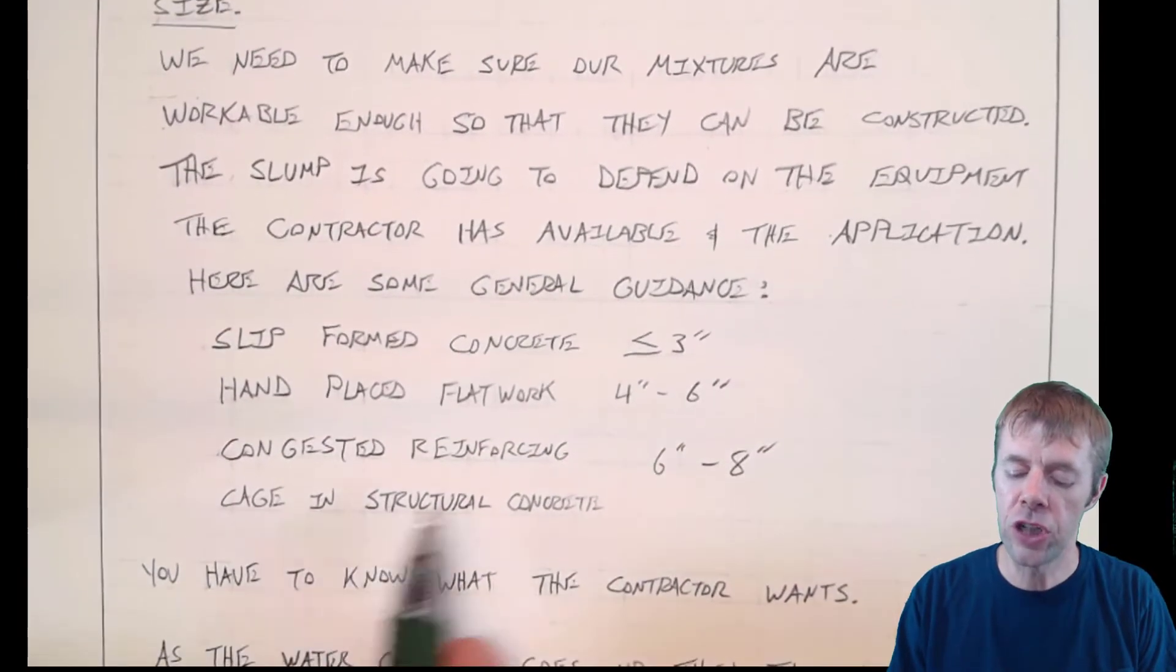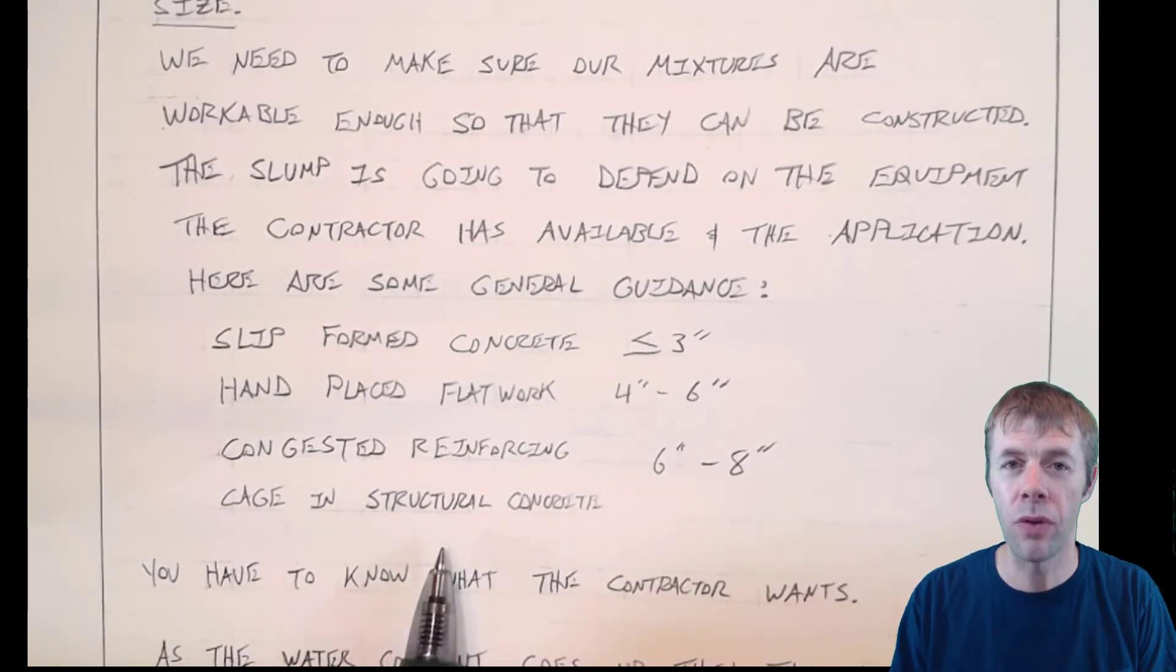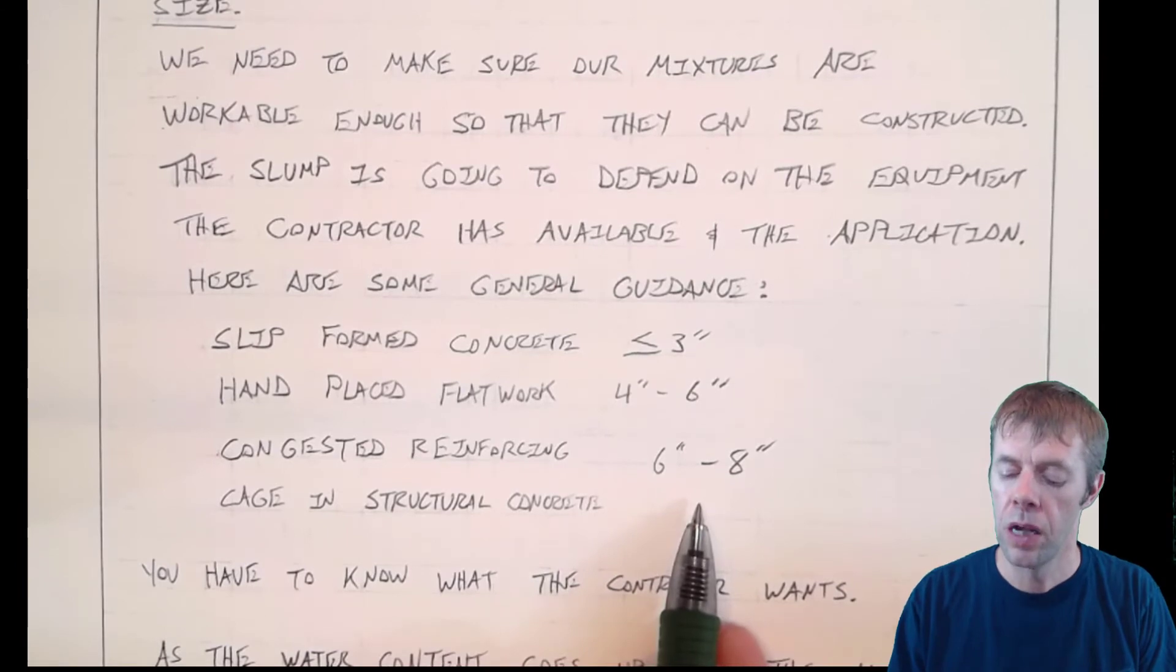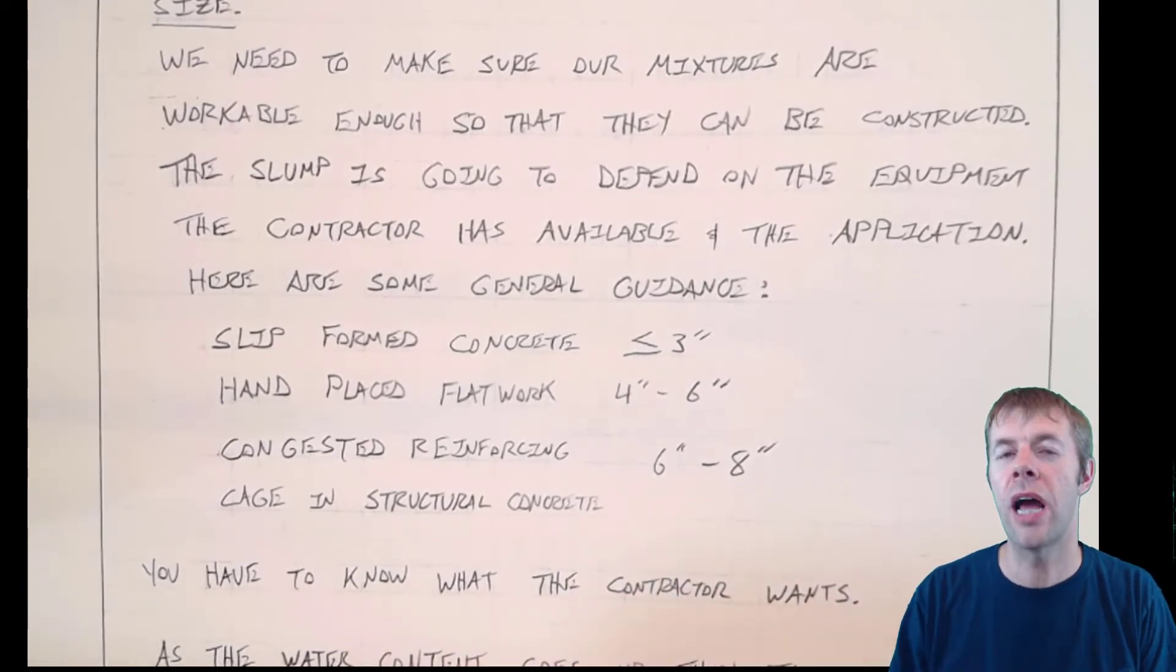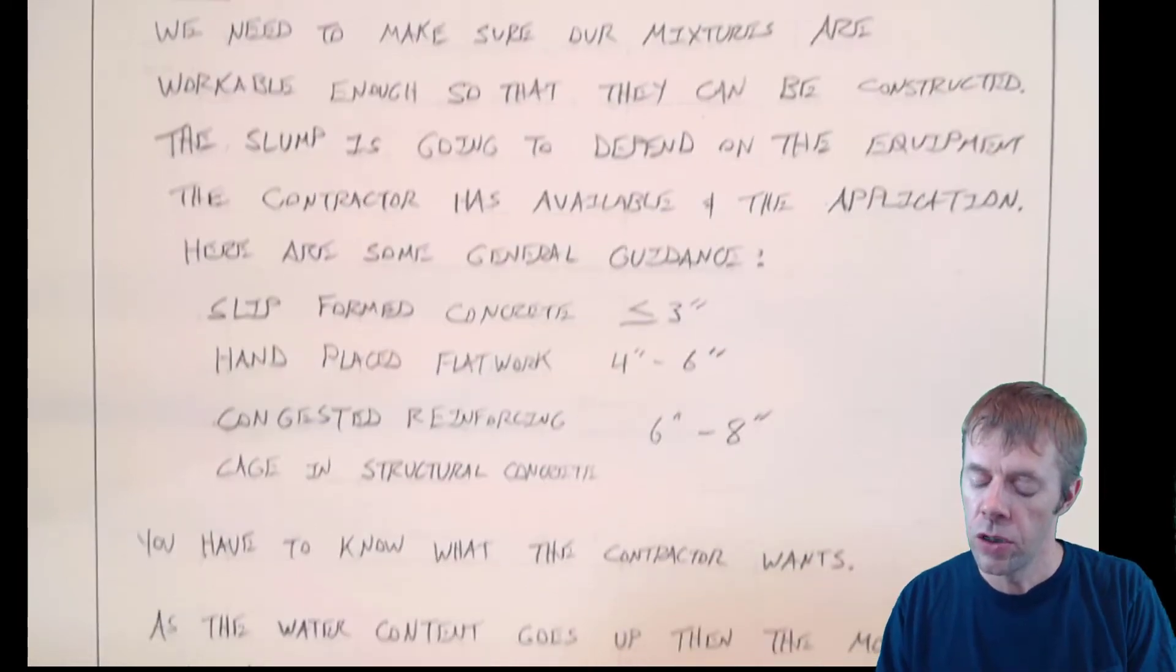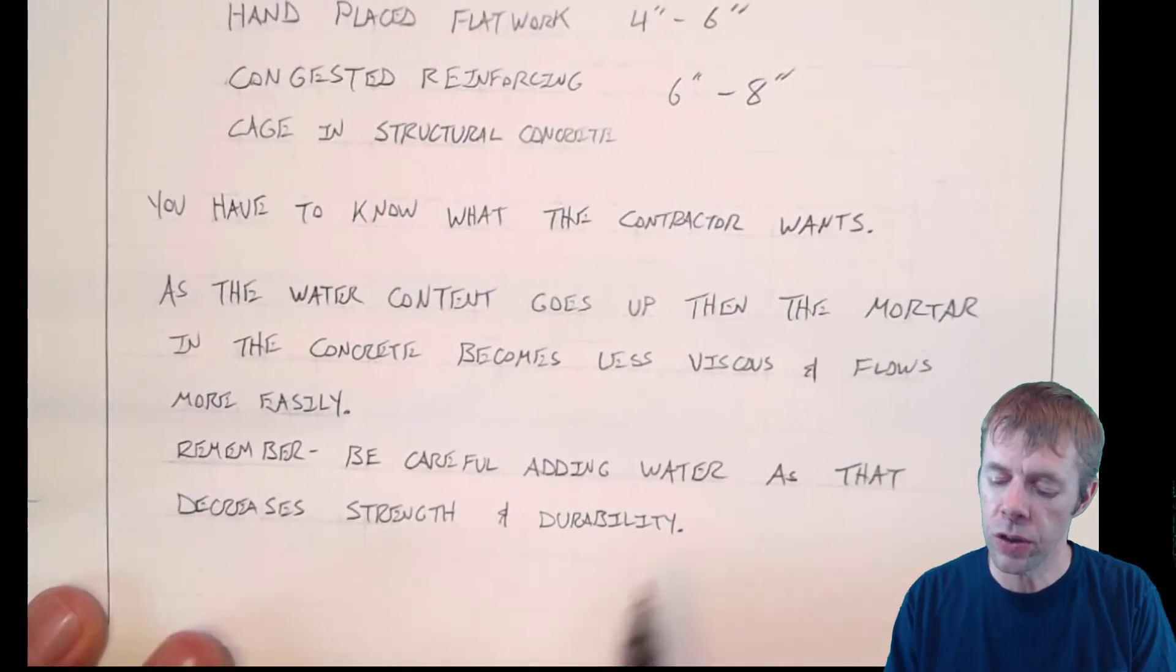If you've got something that's congested reinforcement, maybe in like a structural member, you may need to have six to eight inches. These are all type of things that you're going to have to just ask the contractor what they want or give them a lot of different opportunities to see what mixture design they like.